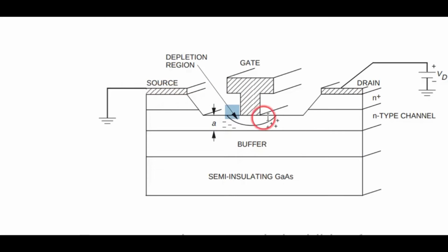Then you do a bunch of patterning with photoresist and all that stuff, and you etch out a channel down to this active layer here, right? And you put on your gate. So this is a Schottky barrier gate, and ours, if I remember right, was a layer of titanium, a layer of platinum, and then all of the rest of this was gold. So most of it was gold, gold being a good conductor that doesn't oxidize.